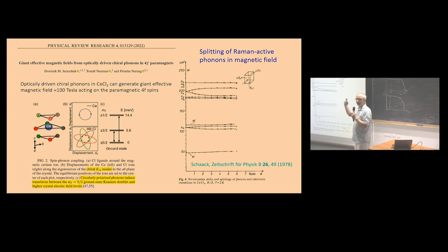You can have a magnetoelectric effect. You can change the permittivity, and you can have a tiny change of phonon frequency. But in this case, there is a splitting, and it is of the order of half a terahertz, so it's huge. And in this paper, they predicted that this splitting should also be seen in an infrared active mode, and we just recently measured it, and we observe it as well. So a phonon around 5 terahertz is split by about 0.4 terahertz in magnetic field. This paper is quite old, 1978, but still valid.